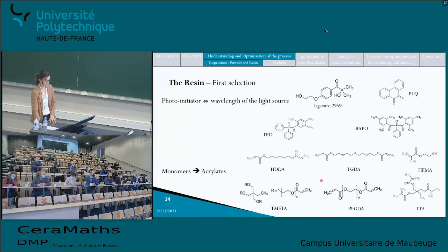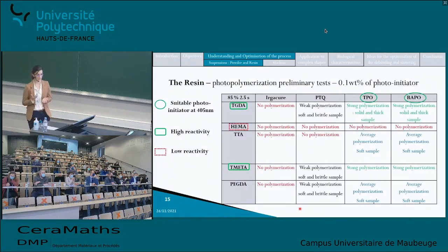Another diacrylate, another triacrylate. I did some first preliminary photopolymerization tests, mixing all of the monomers with 0.1 weight% of photoinitiator. I placed the monomer on the plastic film, illuminated them with the DLP of the ADMAFlex machine, and evaluated the produced sample. So, what first appears here is that the Irgacure and the PTQ did not give the best results in terms of photopolymerization with the monomers used. The TPO and the BAPO enable the photopolymerization of several monomers and are therefore the most suitable photoinitiators to be used at 405 nanometers.